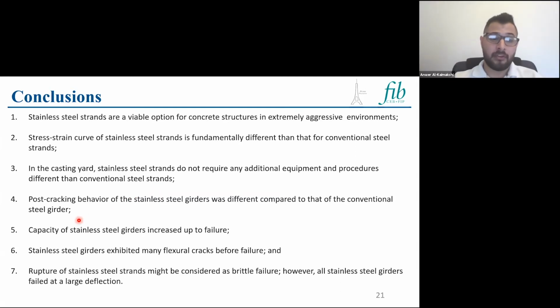From the experimental results, we observed that the post-cracking behavior of the stainless steel girder was different than that for the carbon steel girders, mainly because of the differences in the mechanical properties. The capacity of the stainless steel girders increased up to failure. We don't have a plateau as we usually do for the carbon steel girders.